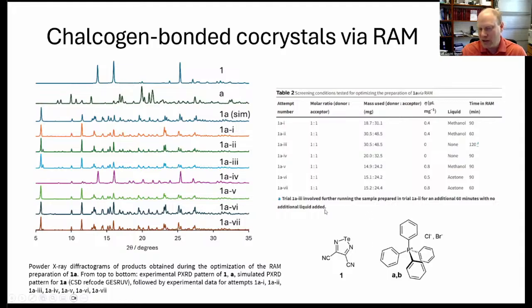So we looked at a whole series of trying to make these cocrystals of this tellurodiazole, again with chloride and bromide electron donors in this particular case, and we went through a whole series of conditions described in one of these RSC mechanochemistry papers. So powder X-ray traces here of 1, of A, and then various products under different conditions. And if you look carefully, through one of these trials, 2 or 3, we're able to get the best agreement. In this particular case, maybe not complete conversion, comparing to 1A sim, which is the actual single crystal trace. So in this case, we were able to get the product almost in every case, regardless of the conditions used. So this was promising.